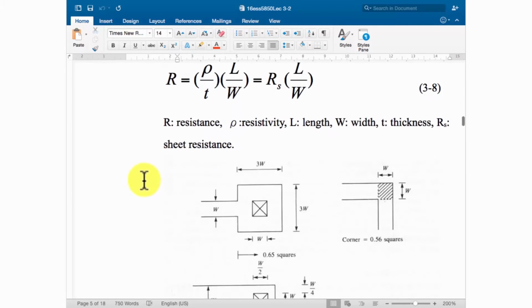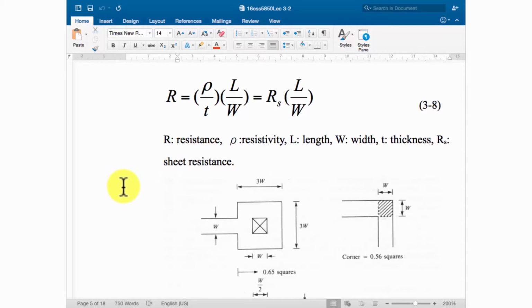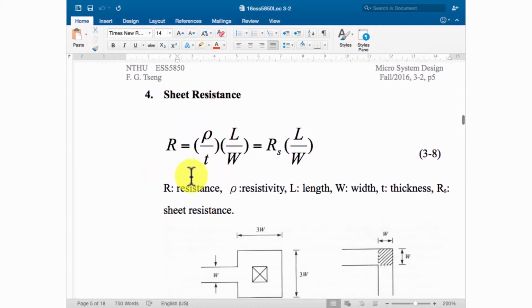But in the IC industry, sometimes the thickness of the resistor is fixed because you go through the same process. You deposit the metal film at the same time, so everybody's thickness is the same. That's why we put the thickness together with the resistivity to form a new parameter. The new parameter we call RS, the sheet resistance. So the sheet resistance means you need only to multiply it by the ratio to get the total resistance. Once we give the value of sheet resistance, when you see a line, how do you calculate the resistance? The calculation becomes very easy because you need to count only the ratio between the length and the width.